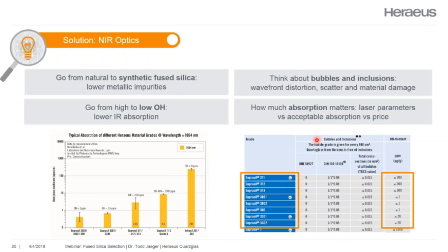So you consider your laser parameters versus acceptable absorption versus price. If you're looking at our spec sheet, you want to look for dark blue, which is going to be your synthetic fused silica. And then we have a column that would be OH content, and it's in parts per million. And so you want to choose something that's on the lower end, and these are our lower OH materials, anywhere from 300 ppm down to less than 1.